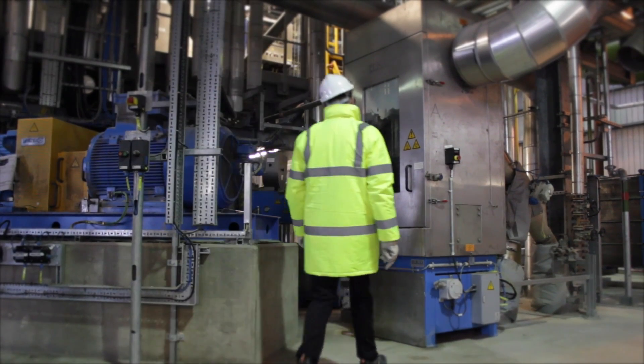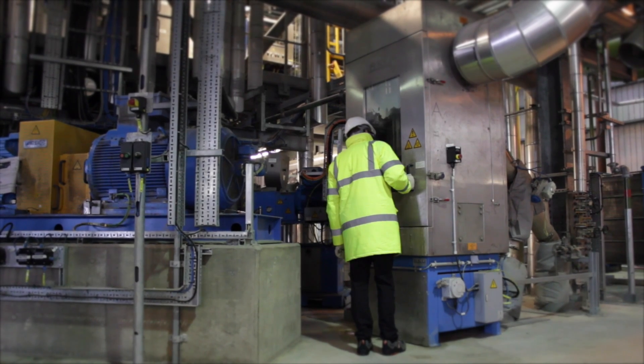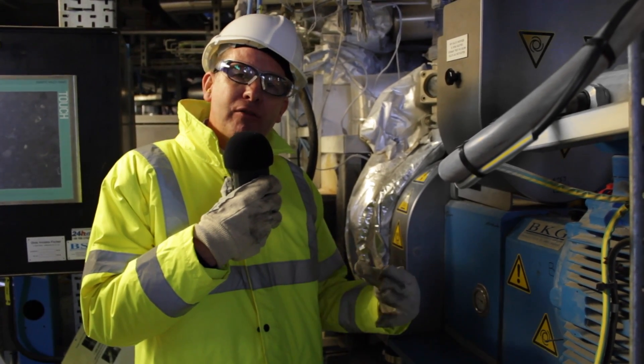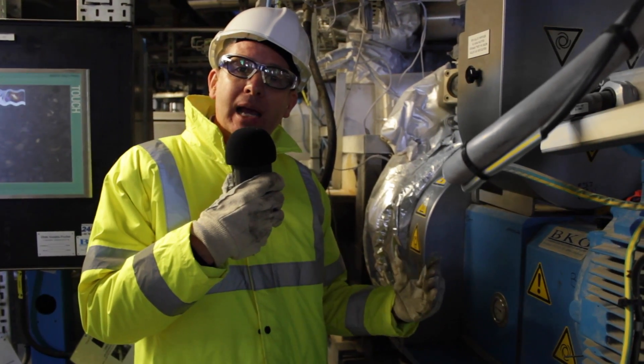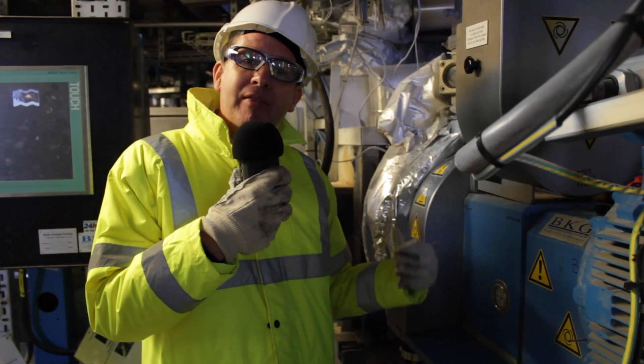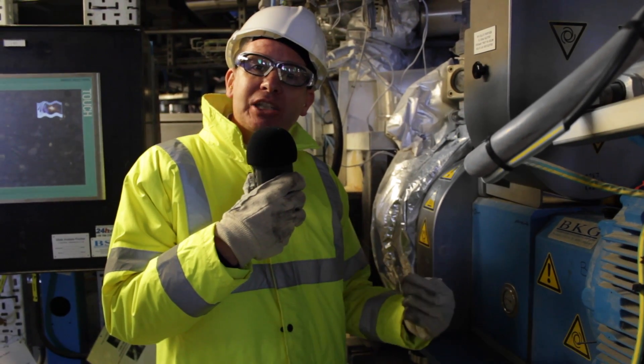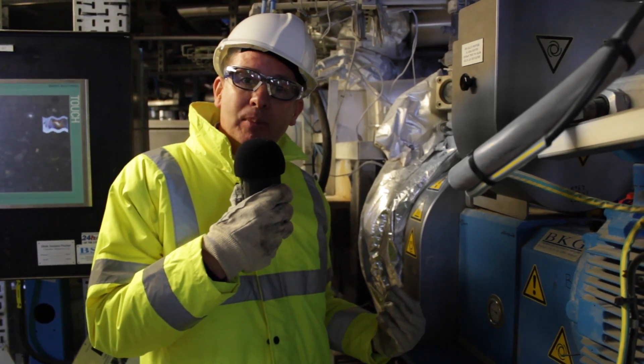We want to retain the maximum amount of heat, so we're utilizing the latent heat to make the crystallization of the pellet. We take the pellets from the cutting process directly to the centrifugal pellet dryer, where they exit at about 140 to 150 degrees C, uniformly crystallized — each and every pellet — in this continuous BKG Nordson CrystallCut underwater pelletizing process.